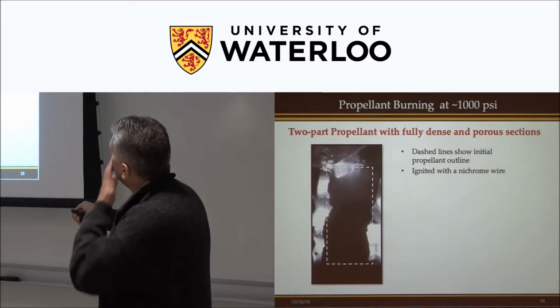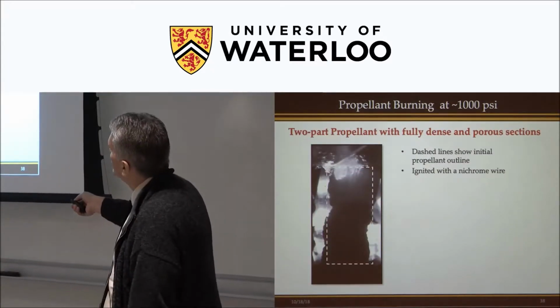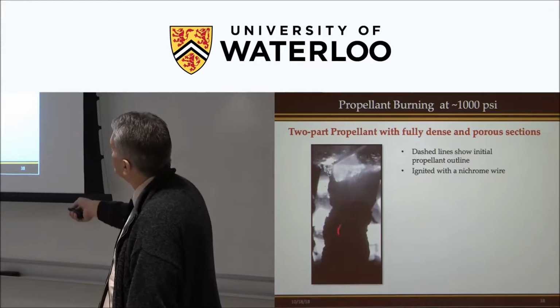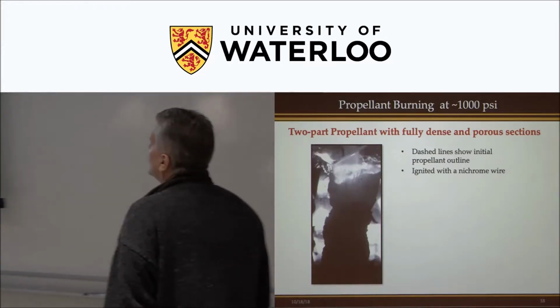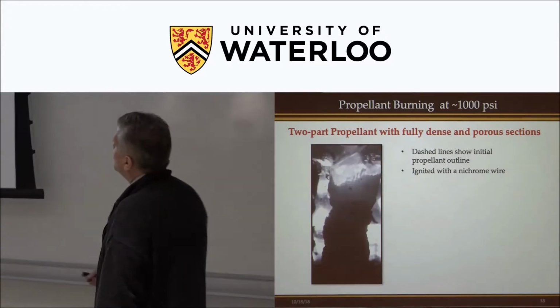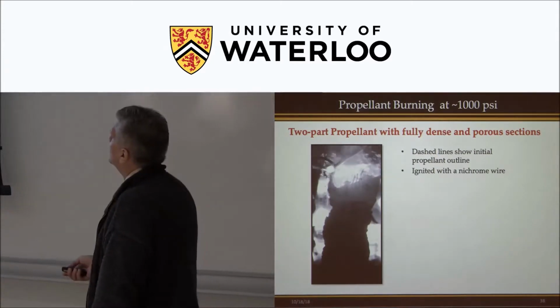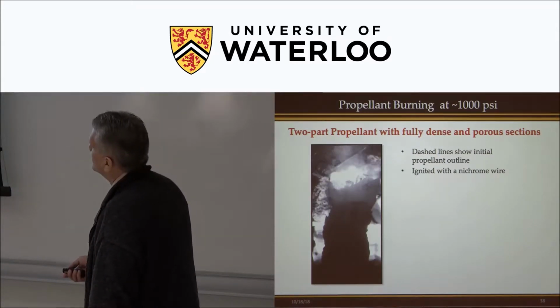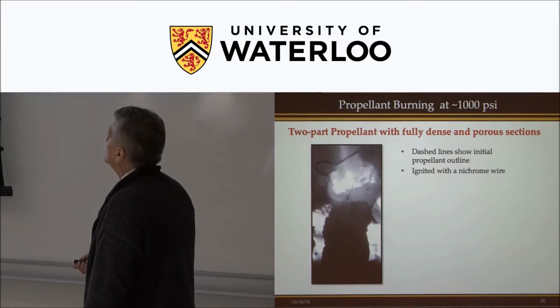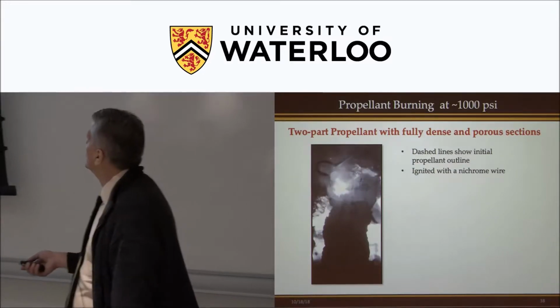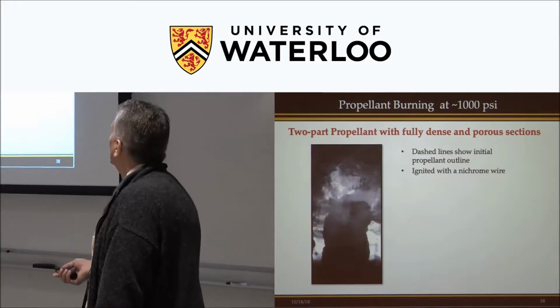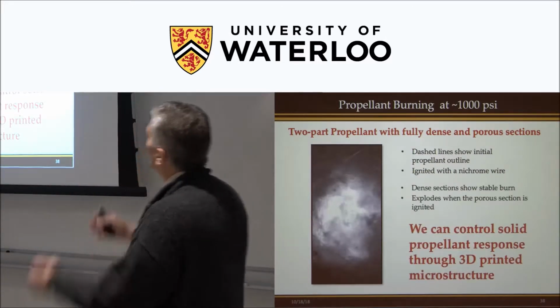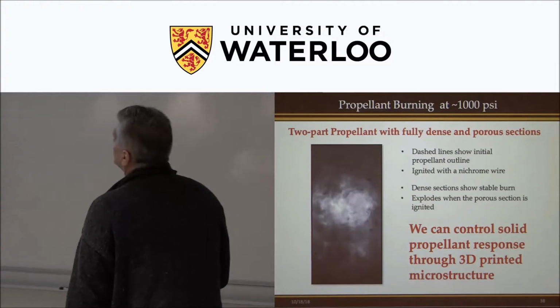So in this case, we have a fully dense case. So this is burning like a normal propellant. It'll get down to this region, and we've intentionally printed some voids into that sample. And there it goes, almost. Once it gets down there, there. So it shoots down through the propellant and basically explodes that.